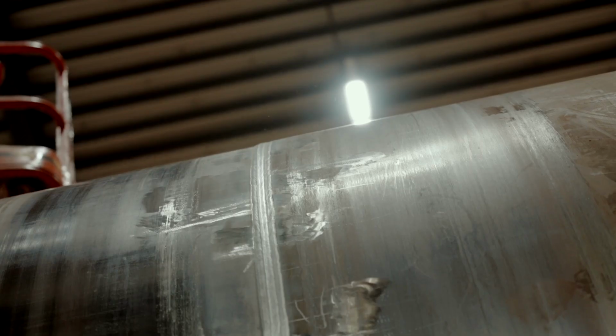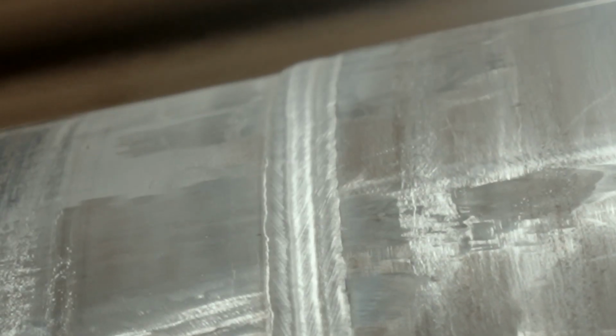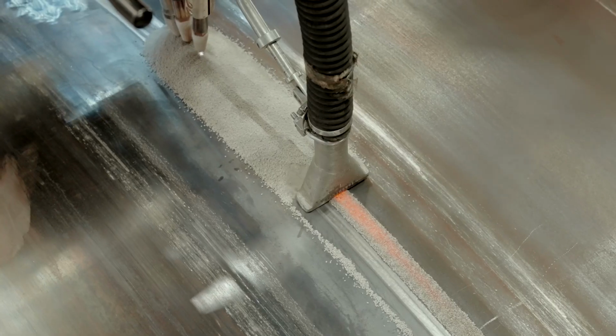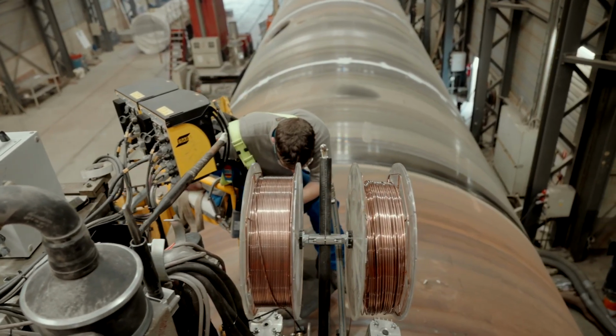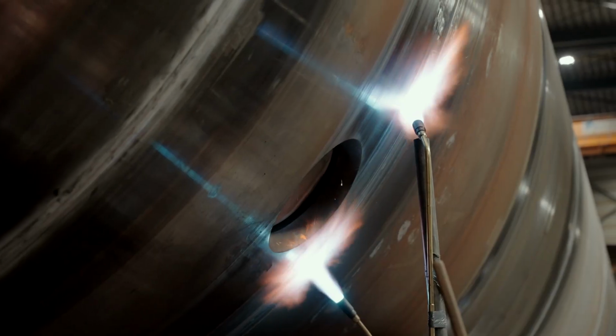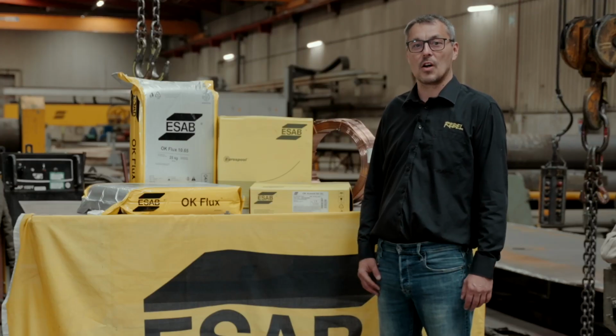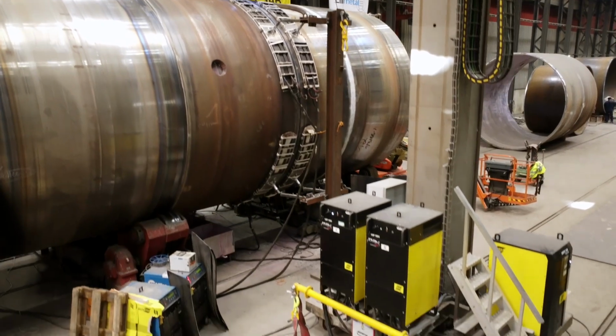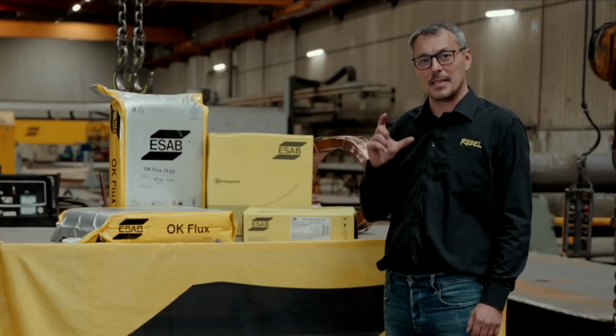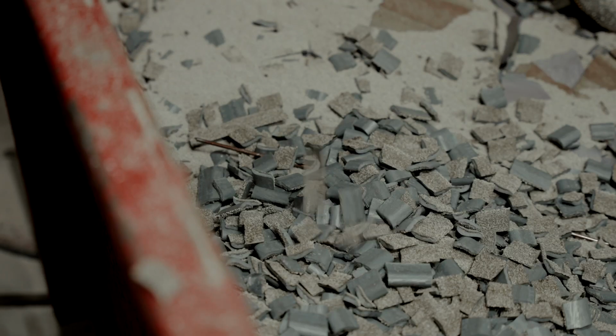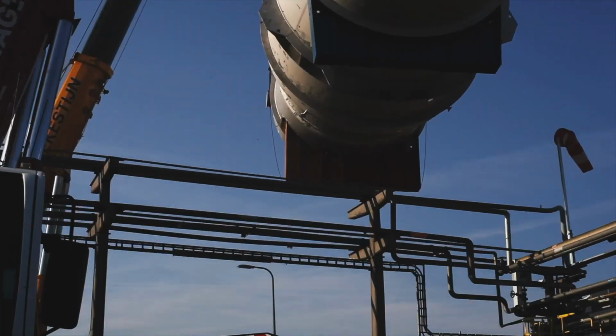After step cooling, high toughness values are achieved with very low level of impurity. For temper brittle resistant applications, this material contains elements providing a X-bar max of 10. After welding, post-weld heat treatment is done and hydrogen levels per 100 grams are lower than 5 milliliters. Designed for single and multi-wire welding procedures on DC and AC current. Narrow gap welding of unlimited plate thicknesses is possible due to a very good slag release. This filler material is suitable for refineries, petrochemicals, chemical industries, power plants, pressure vessels, and many more.